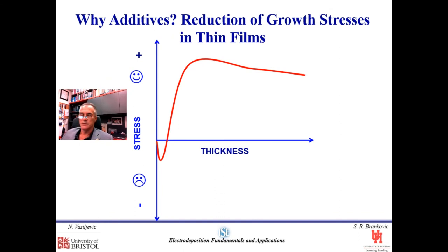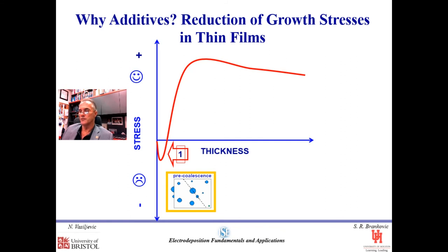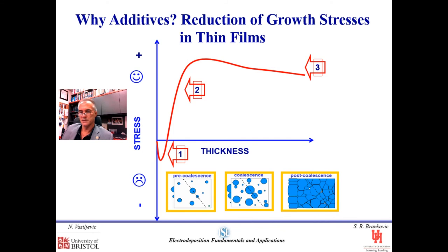Well, one of the important advantages that electrodeposition has, among many others, is not just that we want to have a bright deposit, but that we also want to improve the properties of our deposits with respect to other competing deposition methods. So one of the magics that electrodeposition has using additives is that we can effectively mitigate the level of stress in the deposit. If you think about the stress thickness curve, it's dominated in the very beginning by nucleation phenomena, which drive the stress into the compressive regime. And then as the nuclei grow and start to merge into a complete layer, the grain boundary zipping process defines the stress signature, which goes into tensile relaxation and stays tensile as the film thickens.